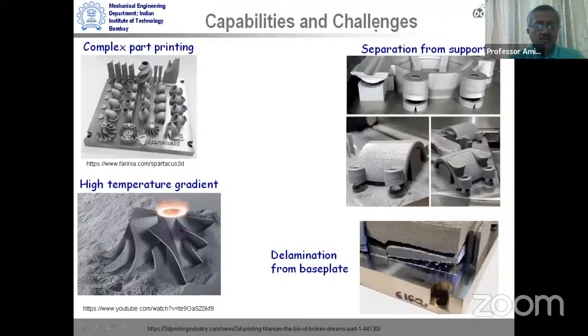On the capabilities and challenges side, we see that these processes as a whole are capable of printing or fabricating very complex parts. That is the prime novelty of these additive manufacturing or 3D printing processes. The part can have much geometric complexity. Of course, there are challenges: because of high stresses that are often generated as the parts are built layer by layer, there can be cracks. The part can be separated from the support, an unwanted separation which can lead to total failure of the part. It can be delaminated from the base plate because of high local stresses generated. So these are some of the challenges which are already faced regularly by additive manufacturing processes. So it is not surprising that these situations will also prevail when we think of utilizing these processes for remanufacturing or repair.